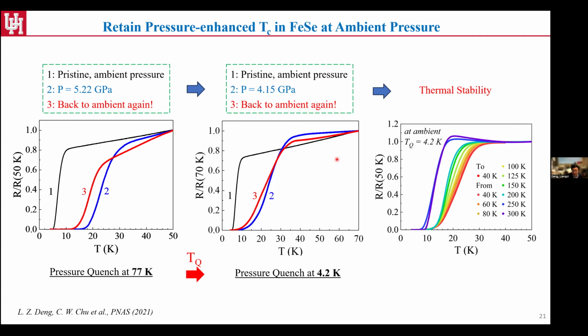So that's why we do the measurement very carefully. I have to mention it's really a lot of effort for our postdocs and students, because in some of the measurements, when we do the thermal cycle, we lose the contact because we don't have any pressure. So this set of data is really all measured on one piece of crystal. We're not trying to combine the results from different crystals together. So that's really a lot of effort to get these nice results. So from here, what we can tell is that once below 60 or 80 Kelvin, the onset TC is almost constant. But as we increase the upper limit temperature higher and higher, the onset TC starts to shift downwards.